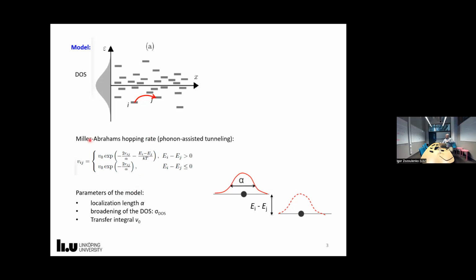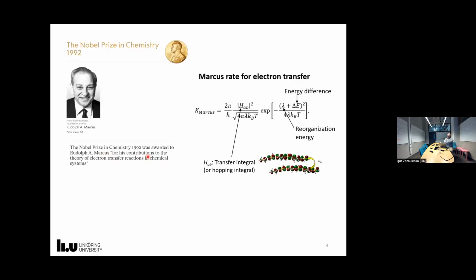And the hopping rate between two different states, in the simplest case, is given by the so-called Miller-Abrahams hopping rate. Basically here you have the exponential form: an exponential dependence on the distance, and also an exponential dependence on the energy difference. I would like to say that this equation is a simplified form of the very famous Marcus rate equation for electron transfer. This equation was the subject of the Nobel Prize in 1992, given to Rudolf Marcus for his contribution to understanding electron transfer reactions in chemical systems. So in this case, we basically have an electron transfer hopping from one polaronic state to another polaronic state.